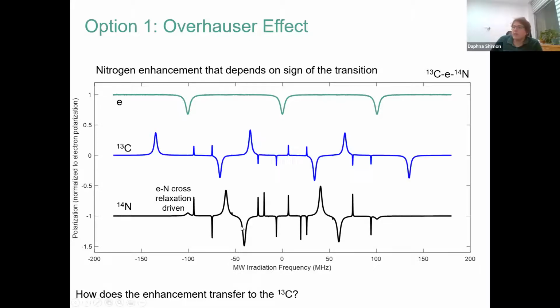The problem is that when I do the simulation on the carbon, the enhancements don't show up, and I haven't figured out a way to have polarization transfer between the nitrogen and the carbon to give us the enhancement here at the correct frequencies without also giving enhancements at other frequencies, which we don't see.